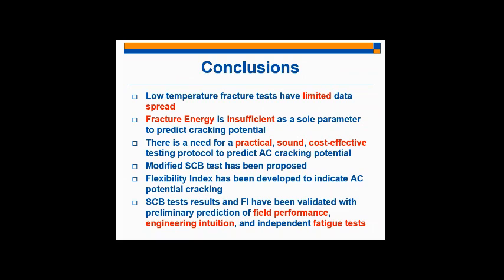And so, conclusions that we've drawn from this study. The first conclusion is that low temperature fracture testing has very limited data spread, so there's a need for addressing the shortcoming. You want to make sure that whatever test you're running, as I mentioned, gives you significant differentiation between different mixtures in the field. Then we switched to 25 degrees Celsius and decided that fracture energy was an insufficient parameter on its own to predict cracking potential because there are complications with misleading fracture energy values. A mixture that would perform much worse in the field results in higher fracture energy values.